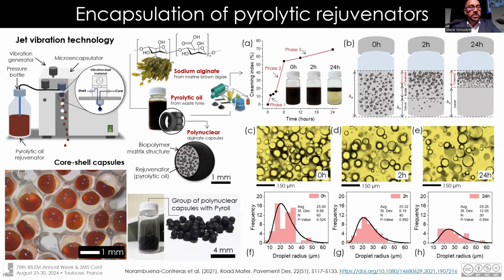You can produce using jet vibration technology. You can produce, for example, polynuclear capsules. You can produce core shell capsules with different purposes. You can evaluate the specific emulsions. You can modify the emulsions with different purposes. At the same time, it's possible to evaluate the mechanical properties of the capsule, not only with specific purposes for asphalt. At the same time, you can incorporate it in coating solution for composite materials as well.